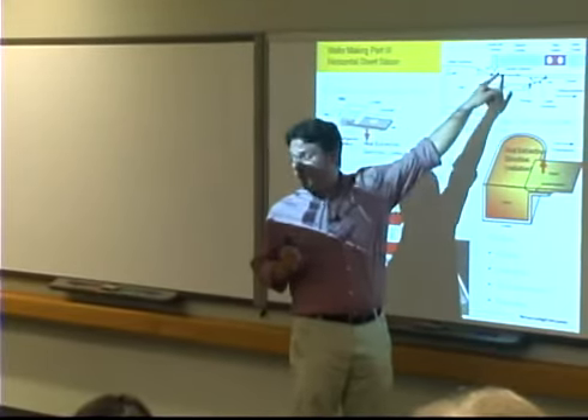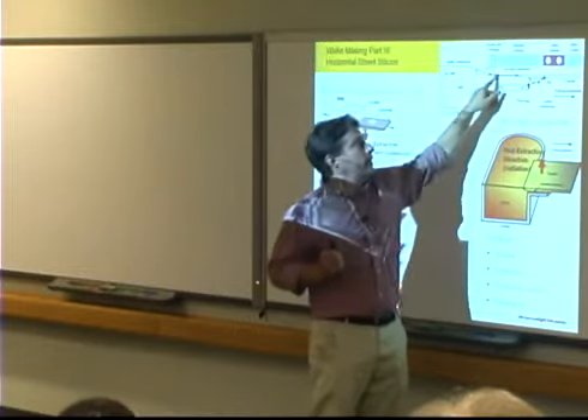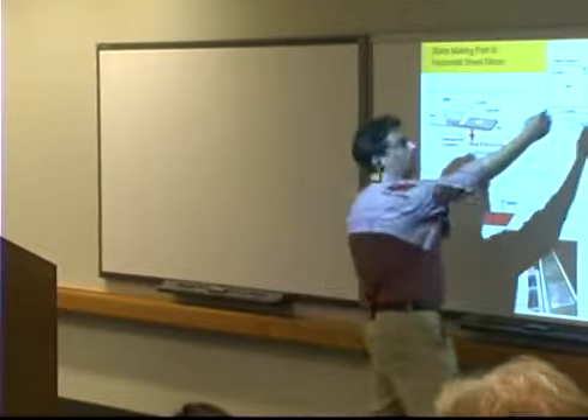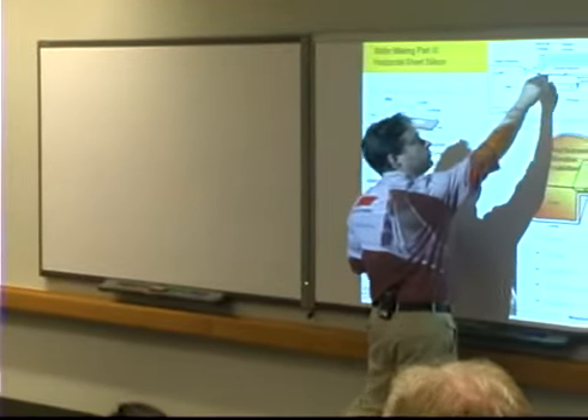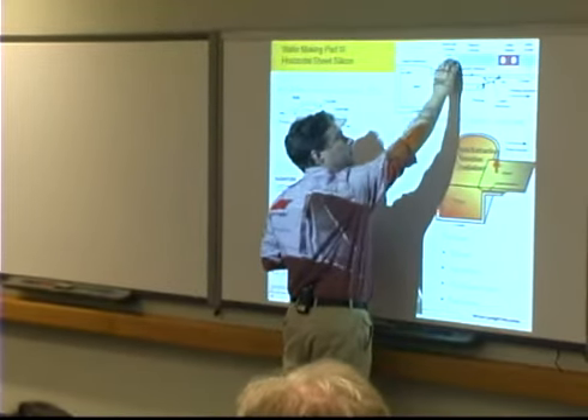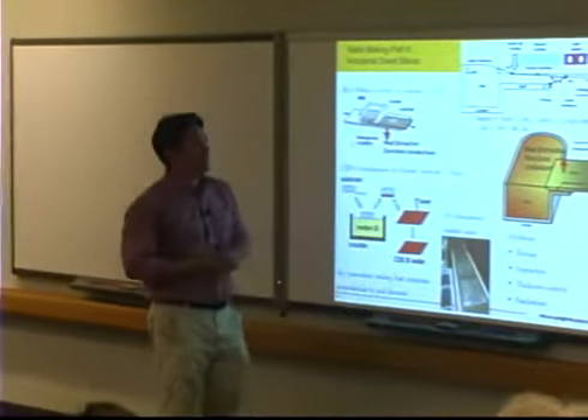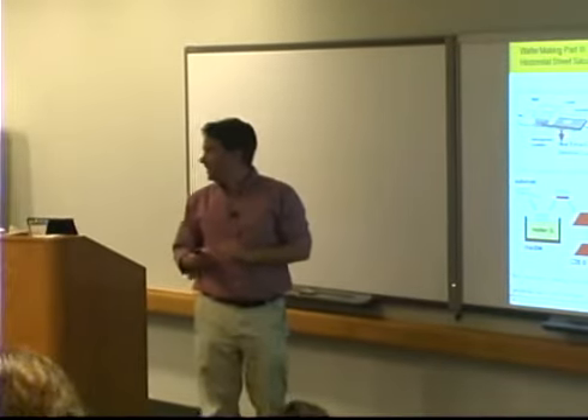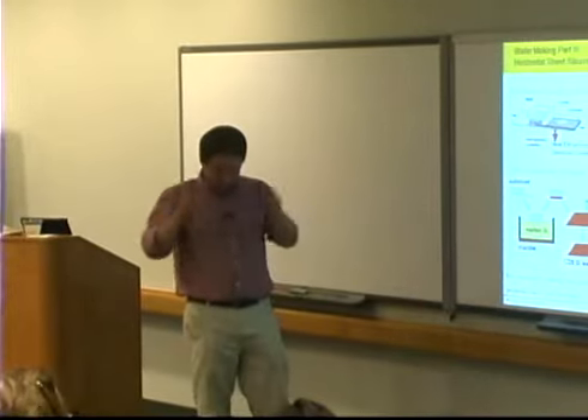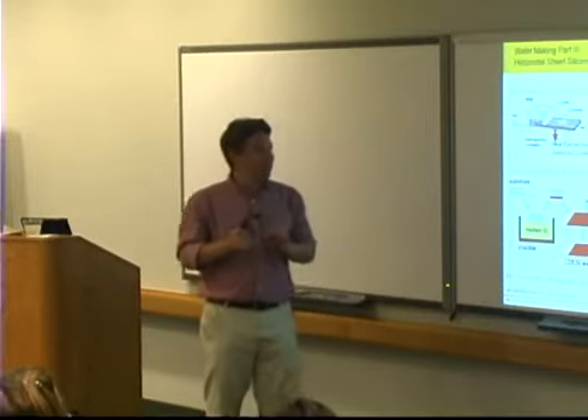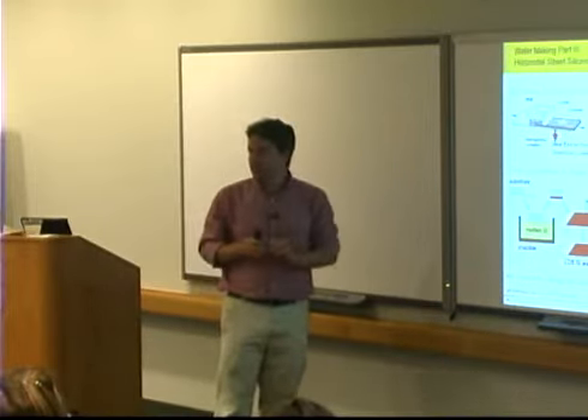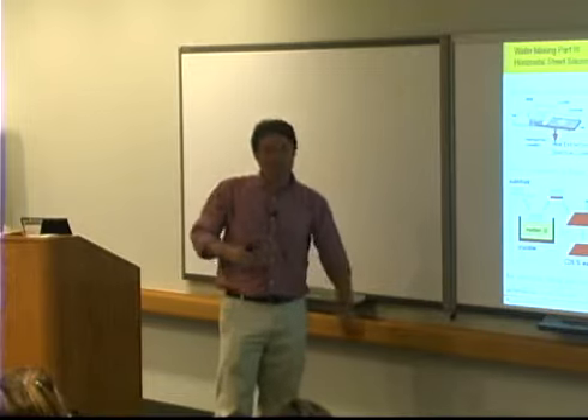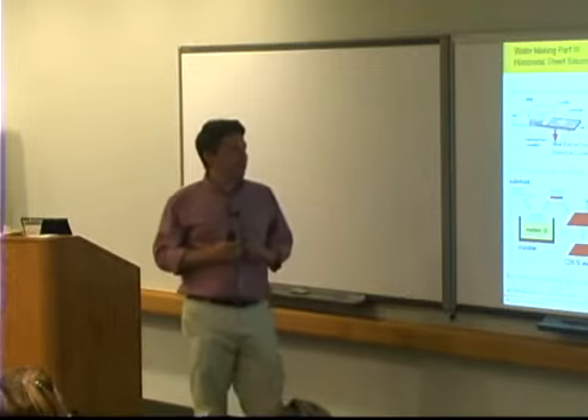was that I couldn't extract enough heat from this little area here, because in order to propagate the single crystal, you have to have the heat extracting out through the crystal, and right at the tip here, what we talked about all the time was, well, we needed a cold laser. We needed something that could focus coldness on the edge the same way a laser can focus heat, and we couldn't come up with a viable way to do that.